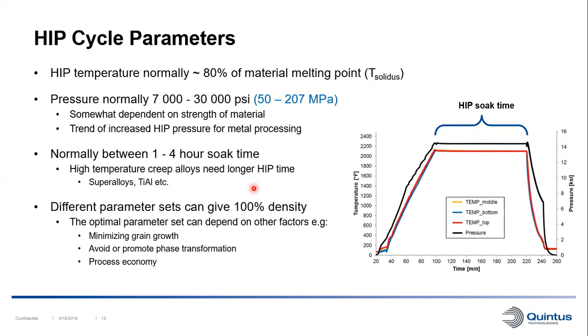So, for example, say that we want to minimize the grain growth in our process, then we would choose as low HIP temperature as possible and as short soak time as possible, and we probably have to compensate by maximizing the pressure. Another example is if we want to avoid or promote a phase transformation to happen during the HIP step, then we would adjust our HIP temperature according to that. And also it can be just process economy. Maybe we want just a cheaper cycle that will achieve the 100% density of our parts.